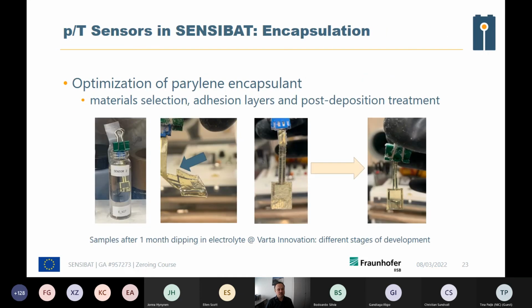What is important for integration, as I mentioned in the beginning, is proper encapsulation. The encapsulation is tested in this case against the electrolyte by dipping it in for several days, up to one month. In the beginning, we found a lot of problems like delamination of this encapsulation from the sensing substrate, wrinkling, and bubble formation.